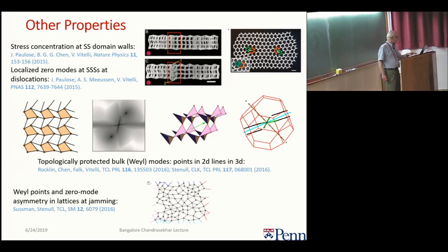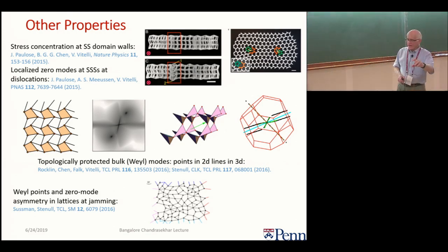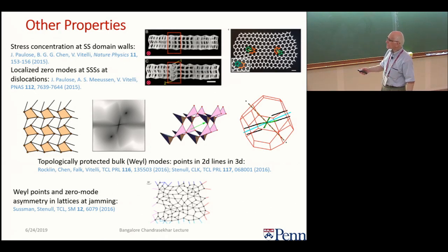different jamming states. You can ask what happens when you put in a real dislocation, in other words, a topological defect in the lattice itself. What effect does that have on the zero modes? And you can have zero modes and associated states of self-stress that go with dislocations and disclinations. If you apply a stress to a lattice which is stacked like this, the stress will be concentrated on the states of self-stress. So if you want to localize where failure takes place in a lattice, you can put in these domain walls with the stress domain walls, and that's where your bonds will first break if you put in the weaker bonds or if you just concentrate the stress there.